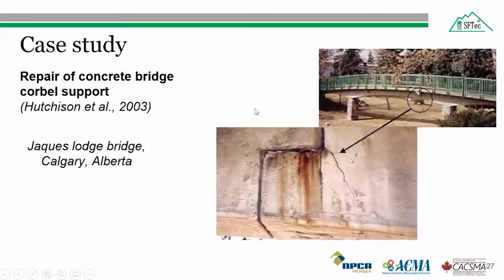So coming to another practical example of the application of carbon fiber sheets, it is the repair of the concrete bridge corbel support of the Jaques Lodge Bridge, Calgary, in Canada. And as shown in this figure, the concrete corbel supporting the main girder had cracking. As you can see here, there is a crack here, and this cracking was due to the unexpected friction forces and a lack of sufficient internal diagonal steel reinforcement. So therefore, to overcome this problem, they suggested external strengthening, because we can't provide any internal diagonal steel reinforcement now.